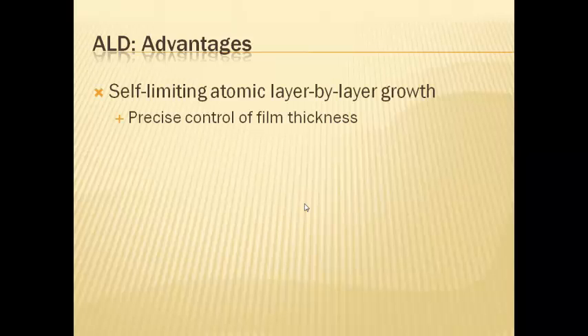As we browse through the different slides, it must have been quite evident that ALD offers a number of advantages that are inevitable in today's fabrication technology. At different points in the presentation so far, we have mentioned those advantages, but it is important to have a summarized view. The first and main advantage is the self-limiting nature of the deposition. As explained using relevant graphics, as the atomic or molecular layer becomes saturated in each pulse stage, a highly controlled layer-by-layer growth can be maintained, leading to precise control of film thickness.